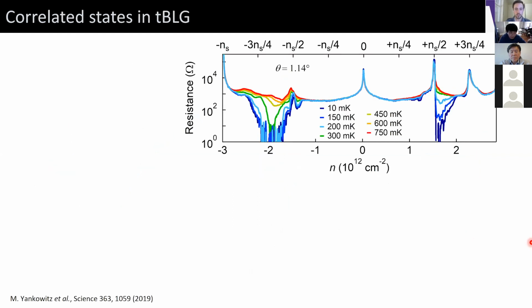Now, of course, the discovery that sparked this field came from the MIT group. I'll summarize with data from my own more recent devices, where if you make a sample at the magic angle of about 1.1 degrees, in addition to the insulating states that you see at full filling, you also see insulating states emerging at commensurate quarter fillings of the bands. And by now we've seen them at basically all of the quarter fillings.